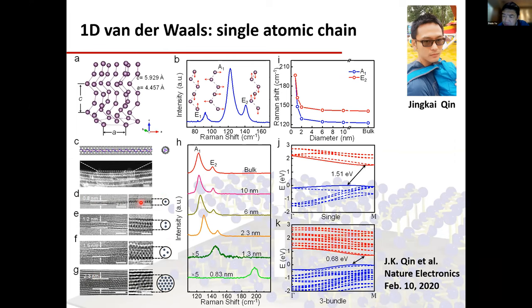And if you take a Raman spectrum of each of these, you can see the characteristic peaks really shifted, okay? Once it's small, it has weak coupling with the wall of the carbon, maybe not strongly coupled, but inside you have more chance for the tellurium to be more coupled to the neighboring tellurium chains, and that gives you the shift. Anyway, theoretical support really tells us the band gap will be changed and the shift can be predicted. It's pretty much consistent.